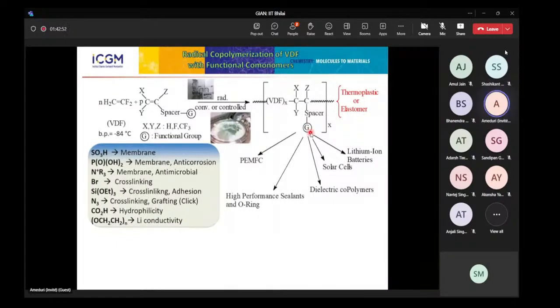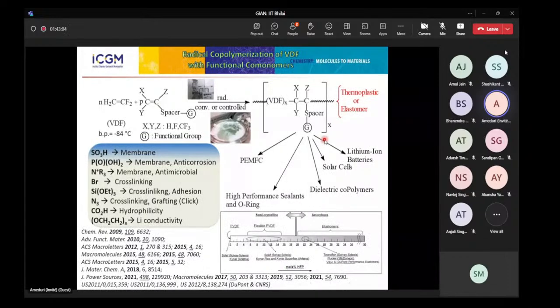In addition, what is very important is that, according to the content of VDF in the copolymer, you can have an amorphous or crystalline compound. And indeed, when you look at the structure of the copolymers based on VDF and HFP, hexafluoropropylene, the presence of a CF3 side group is going to reduce the crystallinity so that you can have an amorphous compound. And this can be used as elastomers. In the case of less than, let's say, 20%, you have semicrystalline copolymers. And of course, these are the different trade names of companies for which these copolymers have been produced. So you have here some flexible PVDF by different companies, and here some amorphous copolymers, such as Technoflon, for instance, or Fluorel or Viton. So this is very interesting.